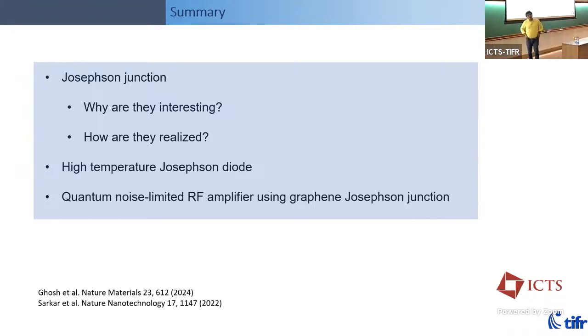I'm curious, the fact that you have a series of Josephson junctions on each side and then rotate. Does that have any implication? Thanks for that question. So you have the intrinsic Josephson junctions. Their switching currents are much larger than the one which is twisted, because this one is the weakest link. When you send current through it, the weakest link pops out first, and then at higher currents, we can see the difference between them. When we make 0-degree control experiments to prove that we have good Josephson junctions, the critical currents or switching current densities are comparable to the bulk ones. So the interface is not getting degraded.